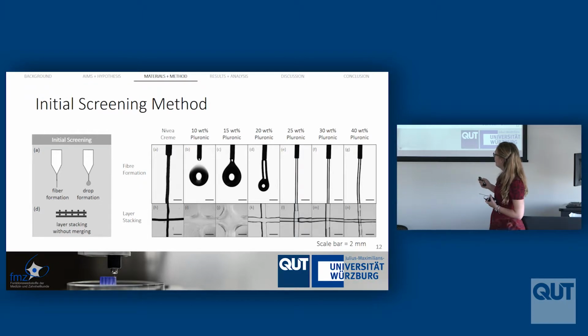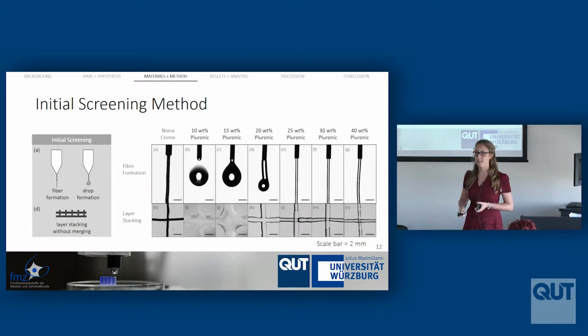So here's our Nivea cream, and look, it gives us an absolutely beautiful fiber, and you stack it on top of each other in a cross and it doesn't start blending together. It's absolutely perfect. Here are some different Pluronic concentrations, and you can see at very low concentrations these are droplets, and as you up them, once we get to 25%, here's our characteristic fiber formation. And also you cross them over and they don't blend together, whereas this one's starting to blend in the corners. And these are basically just liquid on a plate, so that's completely useless to us as well. So very quickly, we can see just by hand, by dispensing these, that we're getting our fiber formation and our layer stacking, which is absolutely critical.